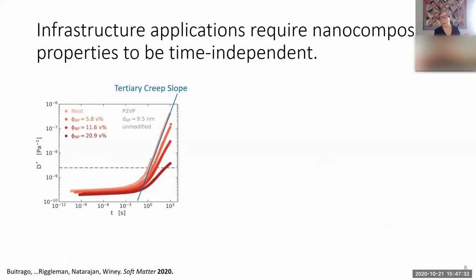So creep is, how much does the material deform under a constant load? And we can look at that by, in this example, doing elevated temperature dynamic mechanical tests, and we're pulling out the compliance. So this is the compliance as a function of time. And first you see that as we increase particle concentration, there's less and less compliance. So there's less and less flow as you put in more particles. But more importantly is how long does it take to get to this dashed line, right? And we can see that it goes out to longer times as we put in more particles.